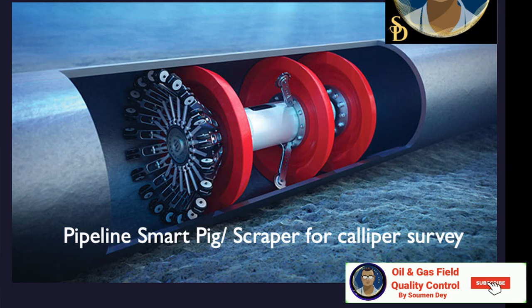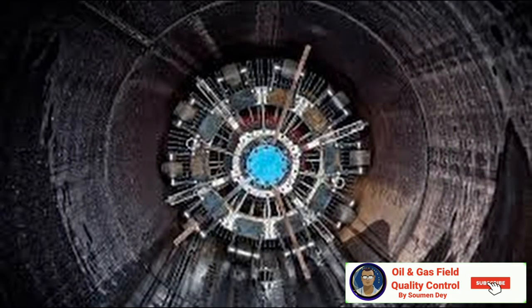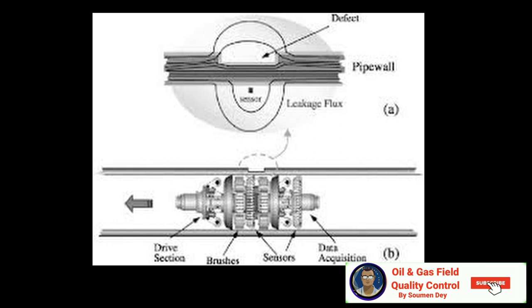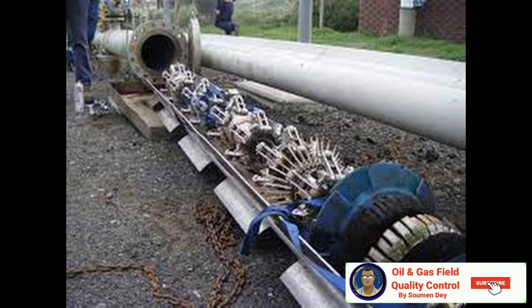Inspection pigs. Inspection pigs, the term of this pigging is also termed as caliper survey, gather information about the pipeline: temperature and pressure, corrosion or metal loss, diameter, bends and curvature, cracks, weld defects, surface pitting, and areas of crushing or deformation. Inspection pigs use two methods to gather information about the interior condition of the pipeline. One is through magnetic flux leakage, MFL, which inspects the pipeline by sending magnetic flux into the wall of the pipe, detecting leakage, corrosion, and flaws in the pipeline. The other is the ultrasonic or UT method, which inspects the pipeline by using ultrasonic sounds to measure the amount of time it takes an echo to return to the sensor.